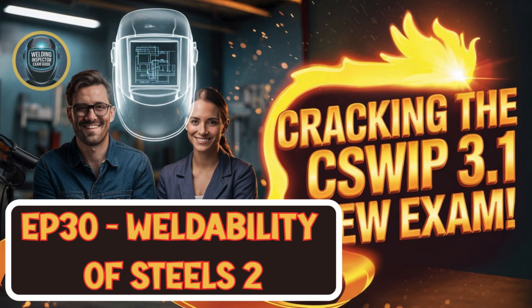There are a few variations, but the most widely used one is from the International Institute of Welding, the IIW formula. It goes CEV equals %C plus %Mn/6 plus (%Cr plus %Mo plus %V)/5 plus (%Cu plus %Ni)/15.